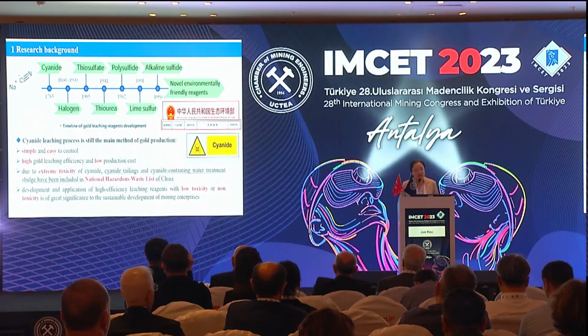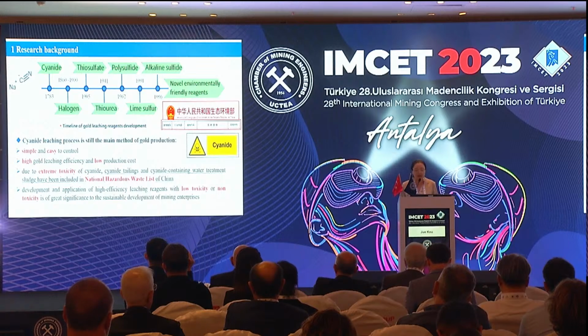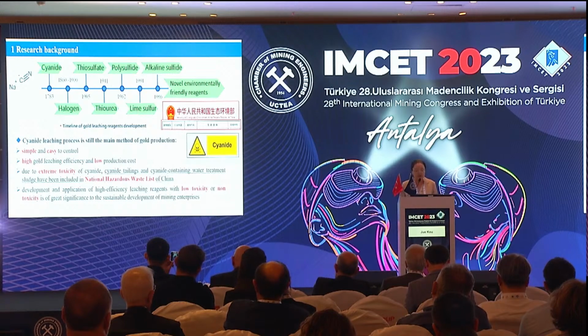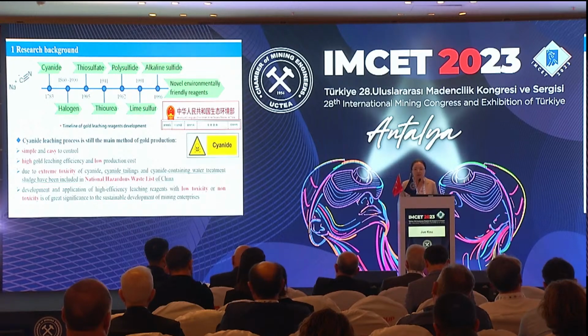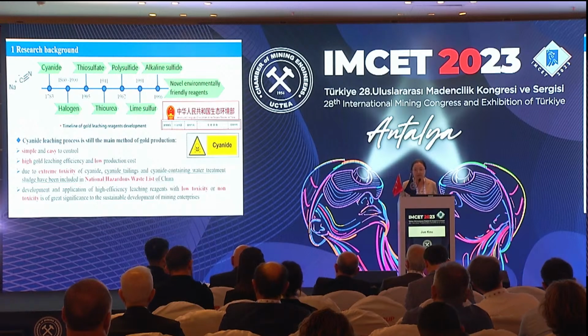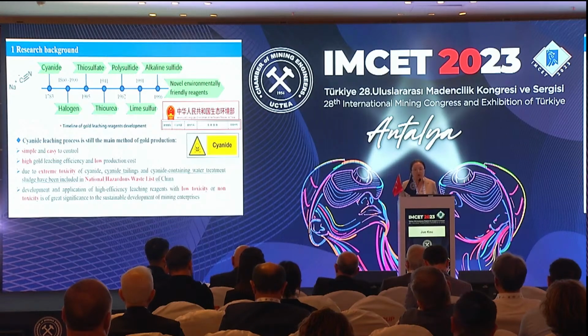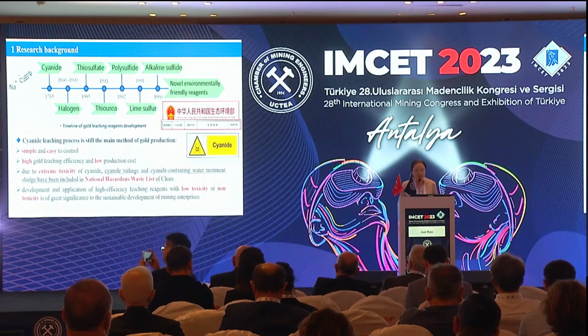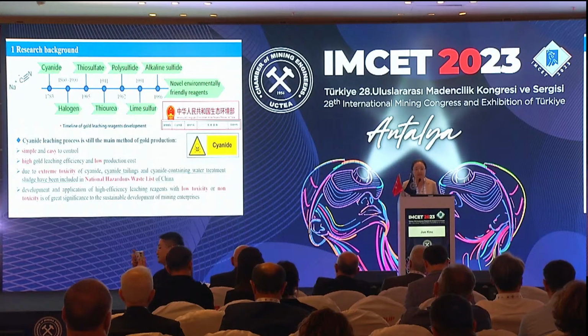For non-cyanide leaching, actually, it also has a long history. For example, the halogen gold leaching starts from the early 20th century, and after that, thiosulfate leaching, thiourea, polysulfide, lime sulfur, and alkaline sulfide, which are considered as the sulfur-containing lixiviants, all started research and application, and in which thiosulfate is considered as the promising lixiviant for gold leaching, which can partially replace the cyanide.